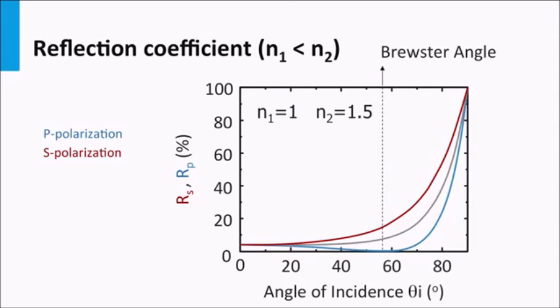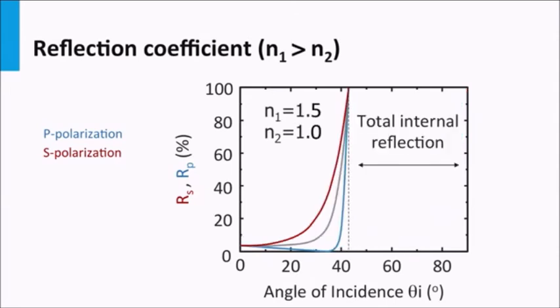In this graph, you see the relation between the reflection coefficient for s and p polarized light when medium 1 has a refractive index of 1, which is equal to air, and medium 2 has a refractive index of 1.5, like glass. What we can see is that the p polarized light has an angle at which the reflection is equal to 0. This angle is called the Brewster angle. The gray line is the average, which represents randomly polarized light.